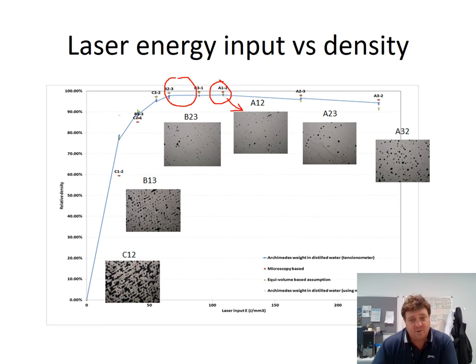And then we can see that as we keep on increasing the laser energy input, we actually start to get this more globular structured porosity. And this is where that keyholing effect is increasing the porosity.